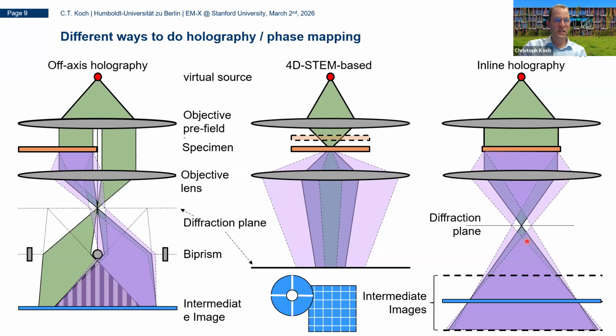Then another technique is this inline holography, where you use images at different planes of focus to overcome the twin image problem, so you can also call this focal series reconstruction. It's also a technique that is widely developed. And another technique is these 4D STEM-based techniques, where you can have, for example, differential phase contrast, which can be executed using a detector like this one, so a segmented detector, or actually nowadays with these fast direct detection cameras, there are also other techniques like, for example, center of mass, which is very similar to this DPC technique, or what I will mostly talk about today, this technique of ptychography.